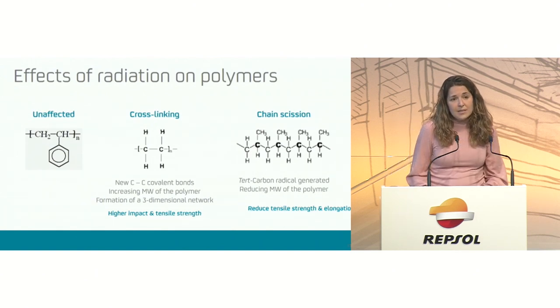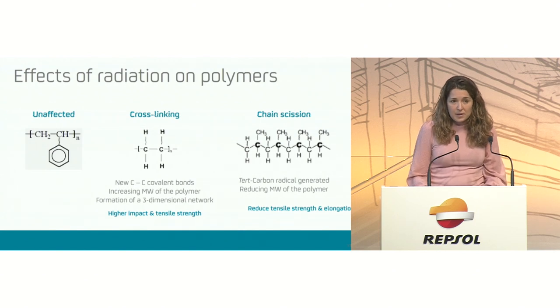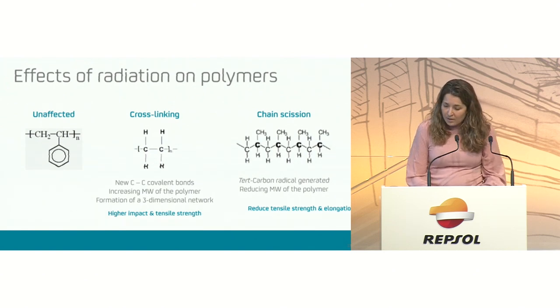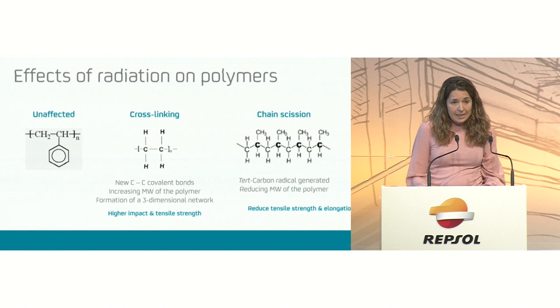If we look at the effects that radiation has on polymers, we must say that each polymer reacts differently depending on the structure of the polymer. For example, polymers with cyclic or ring structures are resistant to radiation effects. Other polymers with carbon-carbon chains, if the carbon has one or more hydrogen atoms attached, it has been observed that cross-linking effects generally occur. Cross-linking reaction forms new carbon-carbon covalent bonds,